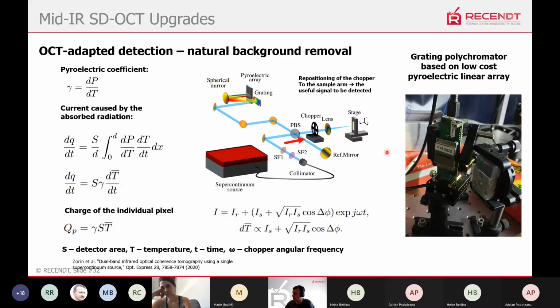The first upgrade was a consequence of using pyroelectrics, which as I said are AC devices, so they're sensitive to changes. At the beginning, I had my chopper, which makes the illumination modulated. I had it at the output of the source, so both arms were modulated, and I saw more or less standard OCT signals where there is a background and you see modulation on top of it. And then I thought, why do I do it like that if I can put a chopper in the sample arm and modulate only the interference pattern in which I'm interested? So we took out this intensity in the reference arm, and then we see only our signals that we are interested in, because delta T would then be proportional to this.